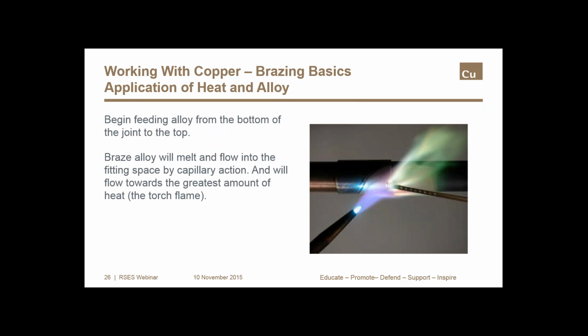It's a good idea to keep the flame away from the filler metal itself as it's fed into the joint. The temperature of the tube and fitting at the joint should be high enough to melt the filler metal. As the filler metal is drawn into the joint, we want to keep both the fitting and tube heated by moving the flame back and forth from one to the other.